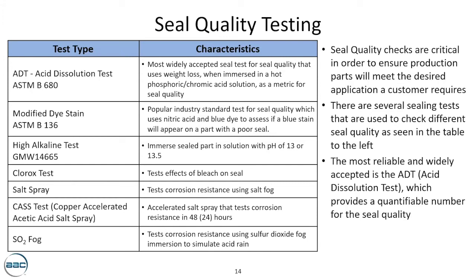Now, from all these tests, the most widely used, most reliable and accepted test is the acid dissolution test, which gives us a quantifiable number for the seal quality, whereas the modified dye stain test only gives us a pass or a fail of the seal quality.